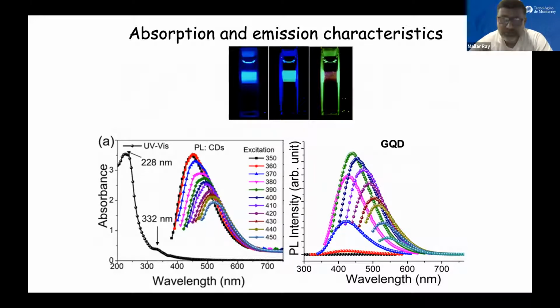Now, these carbon dots, like the graphene dots, like carbon quantum dots, they are luminescent, which means they emit light whenever they are excited by some external energy sources. A typical experiment, very easy to do in the lab, is to do a photoluminescence experiment. So you excite it with a laser or any high energetic radiation, and we can see with our bare eyes that they emit light, they glow. Usually they glow in the blue if you are exciting with UV.